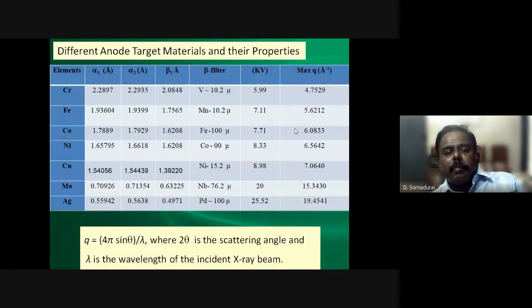So here I made a tabular column about the different targets like chromium and silver, and we have K alpha 1, K alpha 2, similarly K beta and the beta filter. What is the filter we are using for the beta filter? And similarly, what is the critical voltage we have to apply for the characteristic lines? For example, for chromium the K alpha 1 is 2.289, the larger wavelength, and if you go to silver, it is 0.5594 angstrom only, that K alpha 1.